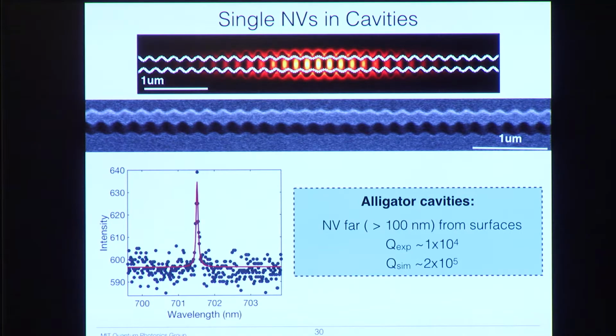And so these cavities have a few advantages. The first is it looks basically exactly like a single mode waveguide. You're more than 100 nanometers from the top, bottom, and side surfaces, and microns from the end surfaces. Also, it's a little bit easier to fabricate, or it should be, because you don't have to create holes. And if you've done a lot of fabrication, creating these high aspect ratio structures is always the least fun part, because you need to etch in these small little areas without ruining your mask.